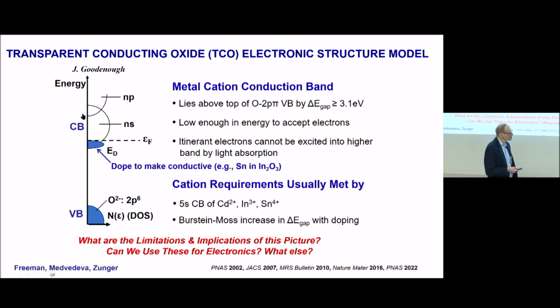For most of these materials, like, say, ITO, these are late heavy metals. The valence band is mainly p orbitals. This is the energy, this is the density of states. The conduction band, say if I had indium oxide, is empty, but the orbitals are very spread out, very dispersed. If I dope it, say to make ITO, then I put carriers here.